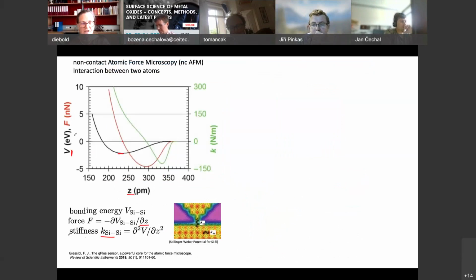So the interaction potential typically is in electron volts. The binding energy between two atoms is something like 3-4 electron volts in a solid. The force between two atoms is in the range of nanonewtons. And then this K, this stiffness, in newtons per meter, is in the range of 150 or so for the silicon-silicon interaction potential, just to give you an order of magnitude.